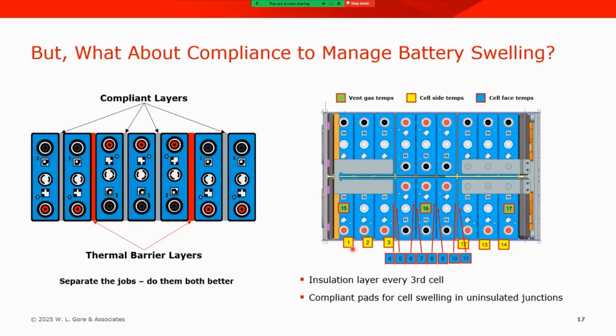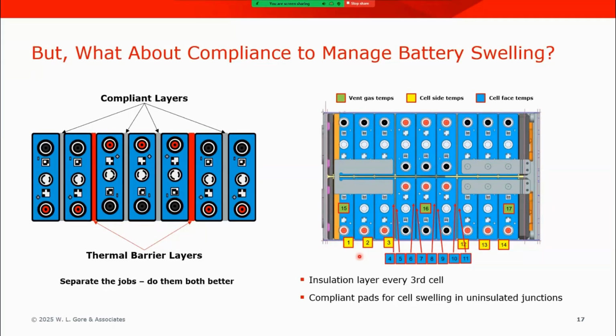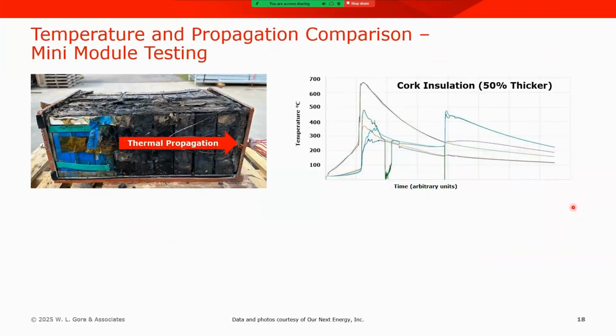Everywhere you see a number, we're going to make a temperature measurement, a thermocouple measurement, so we can determine what are the maximum temperatures that this battery module is experiencing when we put the center cell, number 16, into thermal runaway. So here are the results. First, with an alternative material of cork. And the cork insulation was actually deployed at about a 50% thicker layer than what we're going to compare to GORE battery insulation. So as they say, a picture tells 1,000 words.